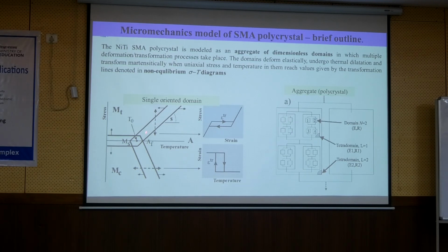So if I have such kind of model for every orientation, but Václav Novák has already measured this, and this is the same for copper, aluminum, nickel, and copper, aluminum, manganese. So we had such kind of model for every kind of orientation and range of stresses, and here it is multiple transformation. So we had everything. The only way was how we connect two grains. I have two grains, so I can connect them in series or in parallel, which is the everlasting problem in the mechanics of materials, with this Taylor and the connection, and neither of them work.